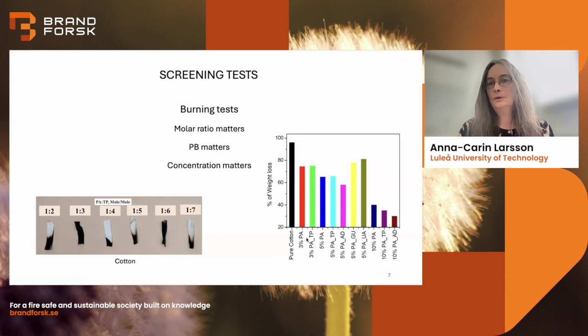We can see that the molar ratio matters from this figure. With different molar ratios between PA and, in this case, theophylline, there is more or less charring. It also matters which purine we have — TP, PA, and PA with adenine — adenine is a bit better than TP, while guanine and uric acid didn't perform very well. The concentration also matters: at 3%, 5%, 10%, more of the mass remains after those burning tests.